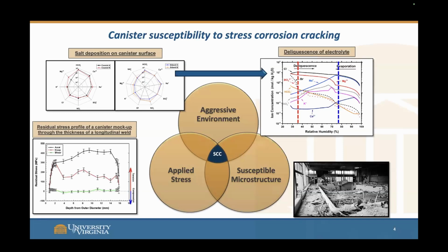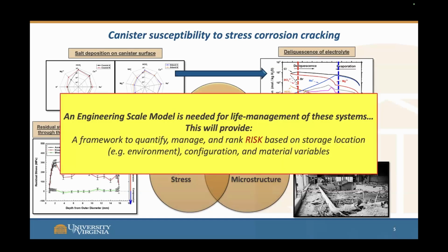And then along with that, the initial canisters were made in the 80s, and they thought it was supposed to be the short-term solution. It is now the long-term solution. So they were not manufactured well, and so there is a considerable amount of residual stress around these welds. And along with this, specifically 304L and 316L were the stainless steels that were used. And we do know from previous literature that these are susceptible to stress corrosion cracking.